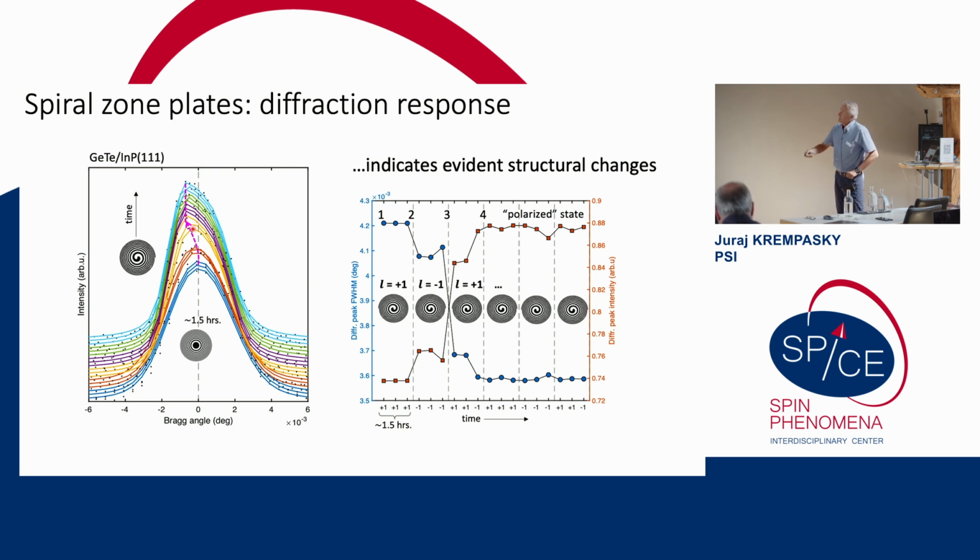At the same time, as I was taught by Václav, what you see here is an imprint of very specific dynamical diffraction, which takes place when the material is going to be perfectly crystalline. So in this time lapse, we started to polarize the material, and eventually we ended up in this polarized state with all the domains nicely lined up.